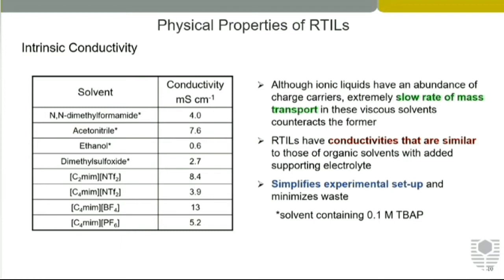And so you would think that ionic liquids, because they're made entirely of ions, would be really, really conductive. But because you have this high viscosity, you've got a balance between the conductivity and the slow rates of mass transport. The advantage of using ionic liquids in this case is that you don't have to add supporting electrolyte. So this can simplify your experimental setup and minimize your waste.